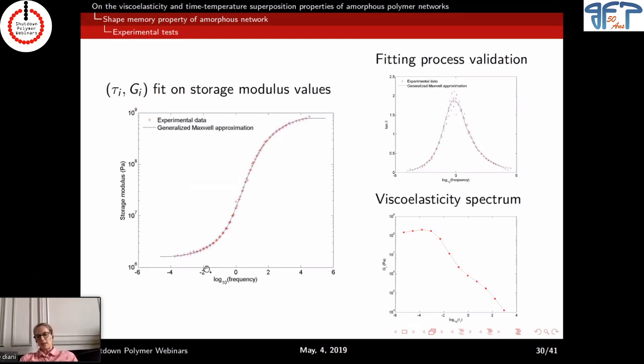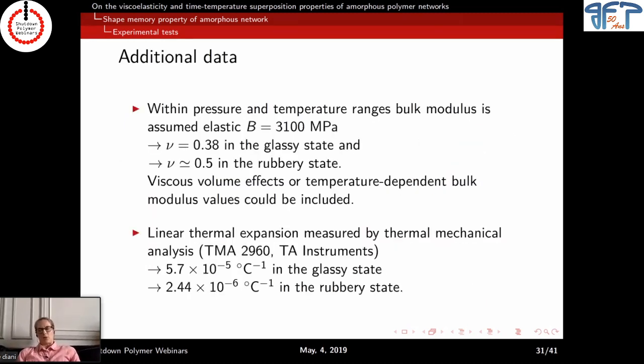With the viscoelastic measure, we fit a generalized Maxwell model on G prime, validate it on tangent delta, and so look at the viscoelastic spectrum, the Gi as a function of the relaxation time. And we needed additional data because we do 3D simulation. So we needed a bulk modulus, and we gave a value that was reasonable to get something that was okay in the glassy state and in the rubbery state. And also, in torsion we don't need it that much, but later in uniaxial tension, we'll need a linear thermal expansion coefficient.